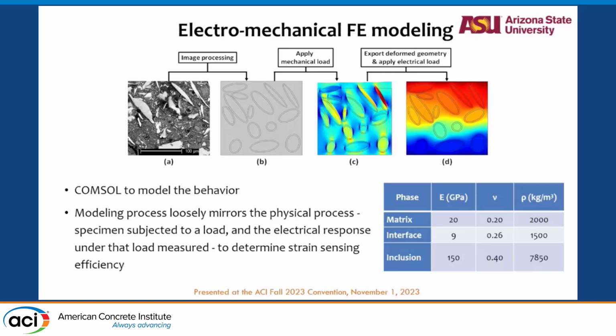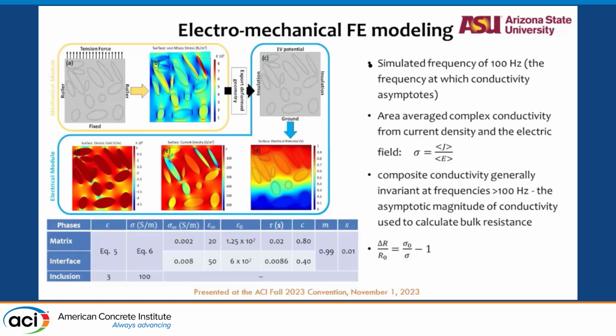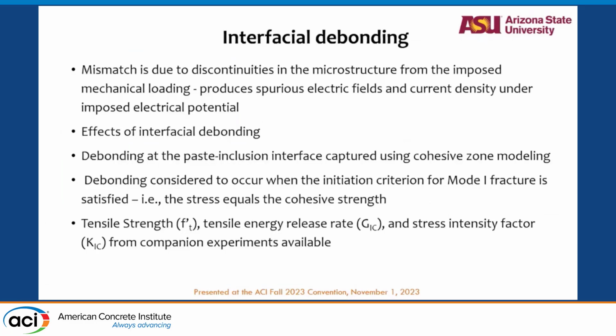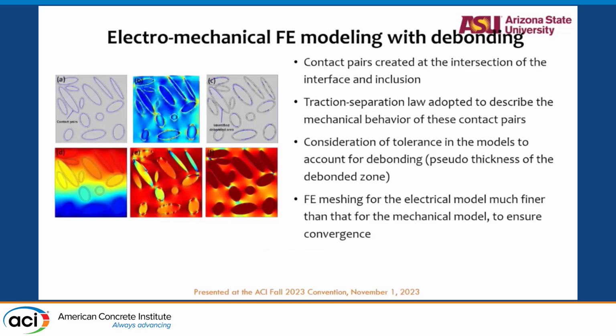This was obtained from a different study that gave us the KIC values, the fracture parameters for the interfaces between the iron powder and the matrix, and non-existing thickness. Basically, a zero thickness cohesive zone was introduced in between the interface and the concrete to model this. Again, this is the debonding issue that I told you had the problem with occurrence.